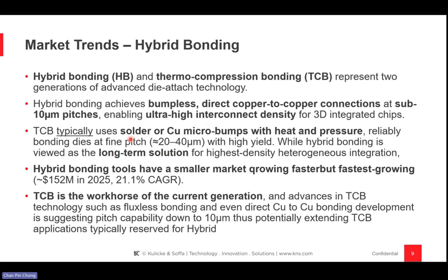TCB typically uses solder, okay, or copper microbumps with heat and pressure. So the key thing here is heat and pressure, right? Reliably bonding dies at fine pitch. Today the market is around 20 to 40 microns pitch with high yields, while hybrid bonding is viewed as a longer-term solution for higher density and even finer pitch for heterogeneous integration. But there are also other challenges with hybrid bonding, which I will explain a little later. Hybrid bonding tools have also a smaller market right now, but it's growing very fast from about 152 million, growing at close to a 20% CAGR rate.